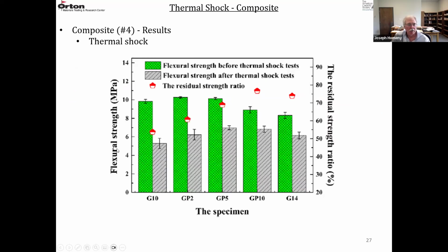So the thermal shock results show flexural strength and then residual flexural strength, the ratio, for the different types of samples: the G10, and then the 4 with the MgO carbon pellets. The green is the strength before thermal shock, the gray is the strength after, and the red diamonds are the residual strength ratio. So usually the higher the residual strength, the better the thermal shock resistance. GP10 had the highest residual strength.